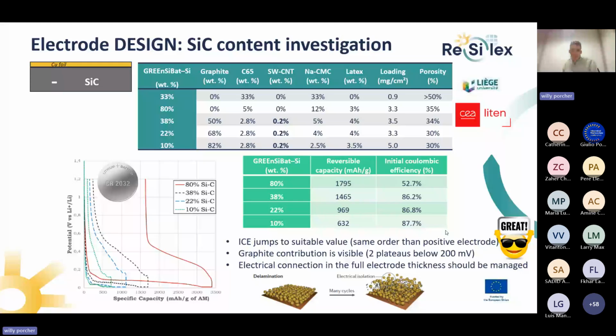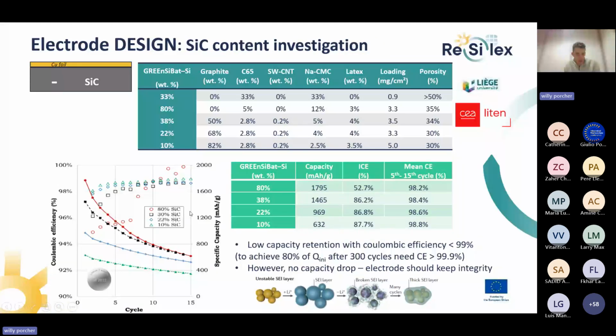However, regarding the next cycles, the capacity is presented here, and you see it's really not a stable capacity. It's versus lithium, and the mean Coulombic efficiency on the following cycles was lower than 99%. And usually, to achieve 80% of initial capacity after 300 cycles, you need a Coulombic efficiency of 99.9%. So here we were really far from that. And we explain it by the interface between the material and the electrolyte, which is not stable.